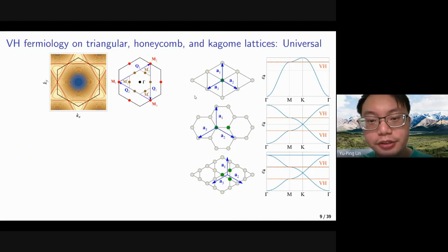So maybe I should explain further the band structure here. For a triangular lattice, we only have one site in the unit cell, so there is only one band. For graphene, we have two sublattice sites, and for the kagome lattice, we have three sublattice sites. So we will have two and three bands for these two lattices. And it turns out that there are two finitely dispersive bands in these two lattices, so there are two Van Hove singularities here.